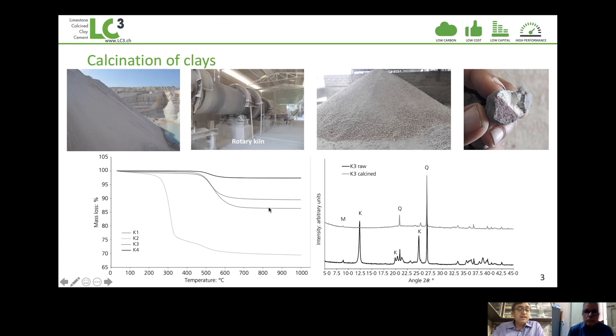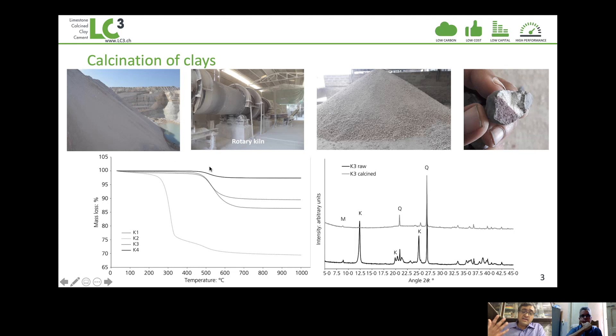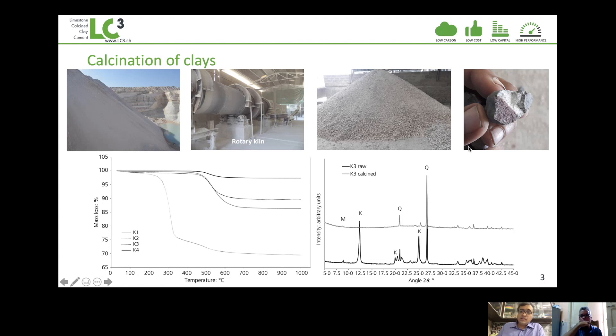You get an amorphous material known as meta-kaolin, which becomes reactive. In the clays we're talking about, this material makes up 40 to 60 percent of the calcined clay. They are usually calcined at high temperatures using different technologies — a rotary kiln, flash calciner, static calciner, and others. After calcination, you can see different minerals formed within the grain. The highly crystalline structure visible in the diffractogram is converted into a more amorphous structure that becomes more reactive in alkaline conditions.